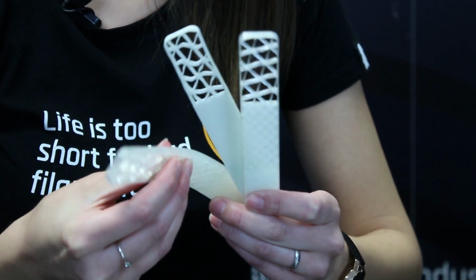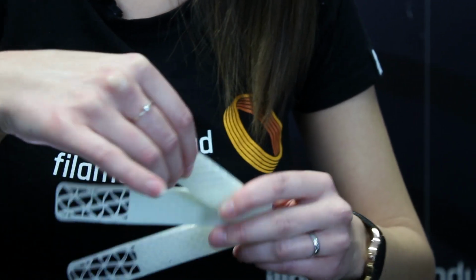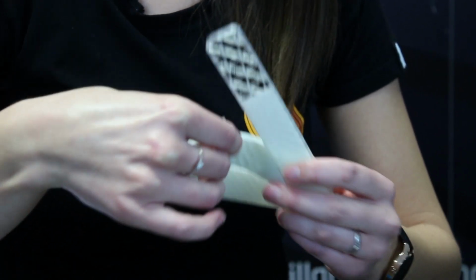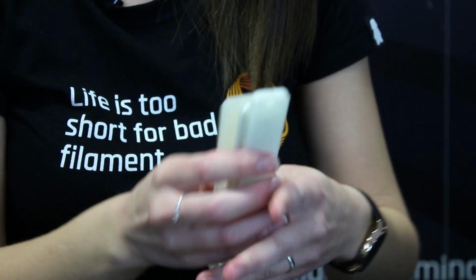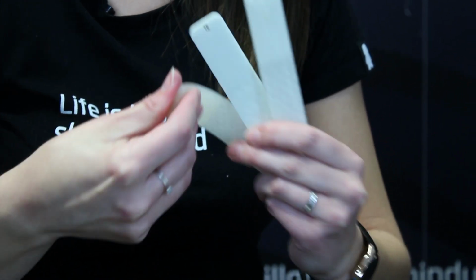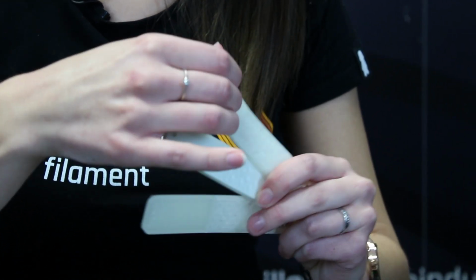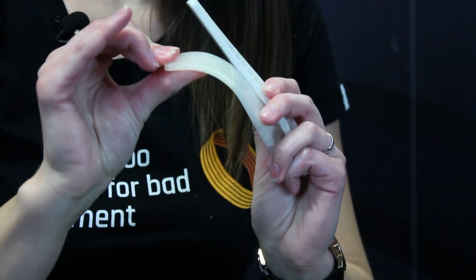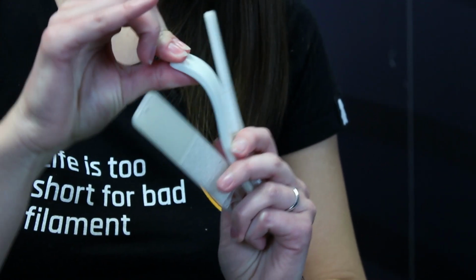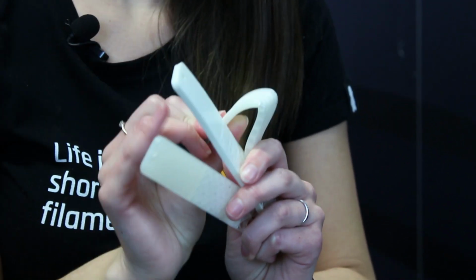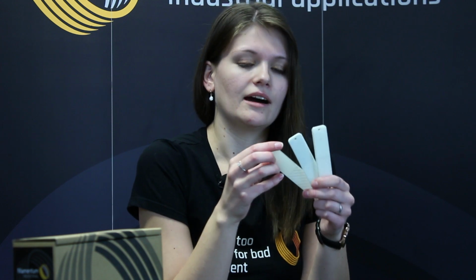This is 30% infill. It is really bendable well, and in 100% we can achieve tough materials, especially in case of PLA. TPE is a little bit more flexible and TPU is the most flexible. So it also is connected with the structure, and we can see that the hardness, as I said before, doesn't influence at all this bulk behavior.